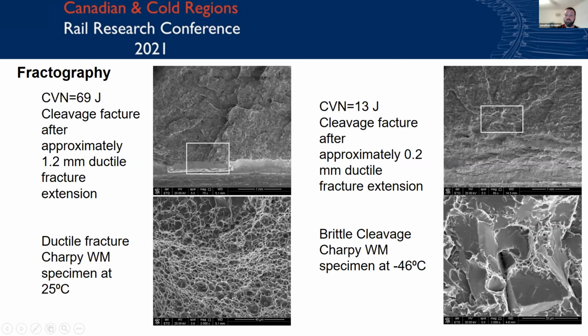In this next slide, I am showing the fracture surfaces of two of our Charpy impact tests at different temperatures, and both have two different levels of magnification, lower level of magnification on the top, higher level of magnification on the bottom. On the left-hand side, you can see ductile fracture at 25 degrees Celsius, and on the right-hand side, you can see brittle cleavage fracture at negative 46 degrees Celsius. The left-hand side, ductile, absorbed 69 joules of energy, while on the right-hand side, it was 13 joules of energy.